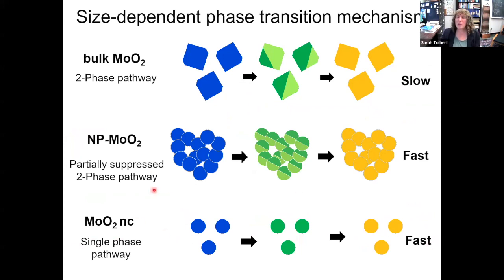But I actually showed you that the medium-sized samples were pretty fast as well, but they did have a phase transition, a discontinuous jump. How can we make sense of that? The answer is probably they never have a phase front that's moving like this. Instead, individual nanocrystals sort of transform at once, and that jump is because of the variation in our sample. But both of these two mechanisms are really fast.